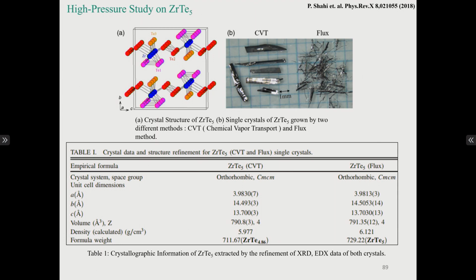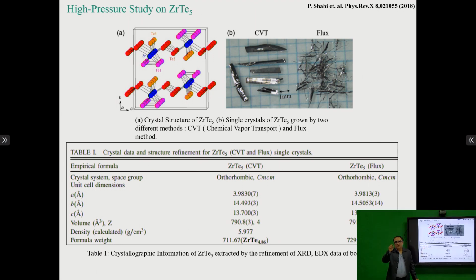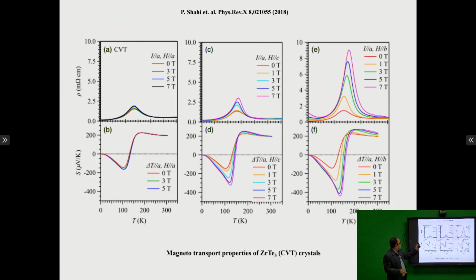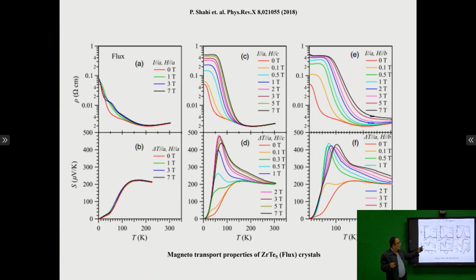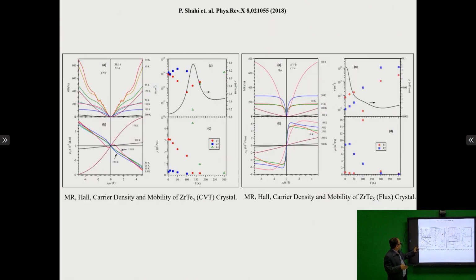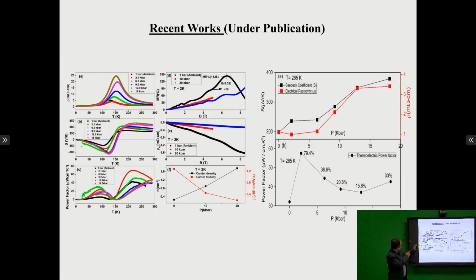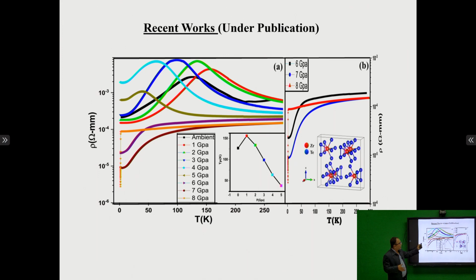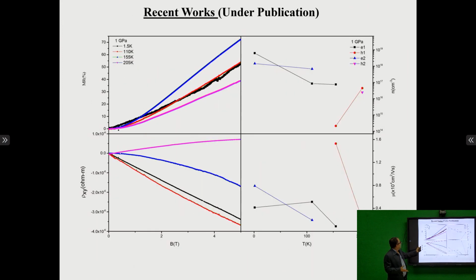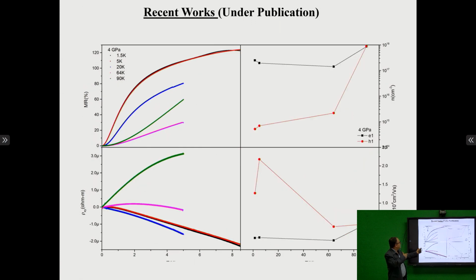In the flux method, instead of using some other transport agent, the material itself works as the transport agent. That's called the self-flux method. We grow the two types of crystals and then perform measurements on both with a magnetic field using the same setup. This one is published, but these are the high pressure measurements we performed in ZrTe5, with some improvement in ZT, and they are under publication. We have communicated it, with nearly the same type of results.